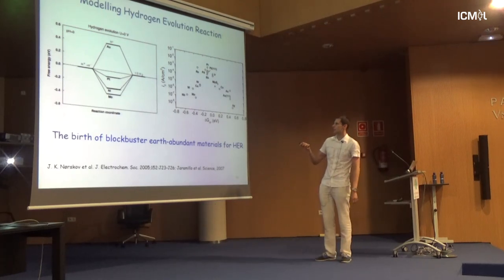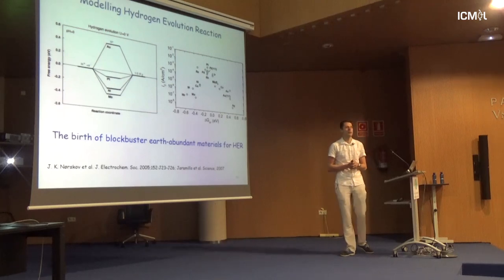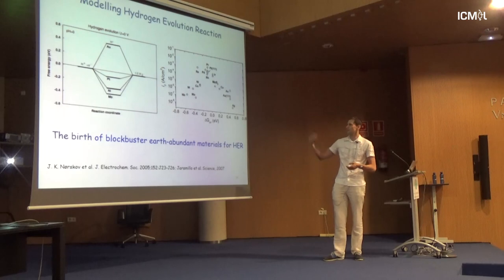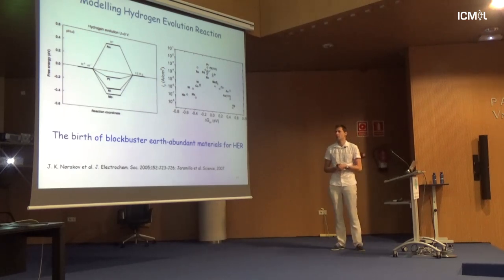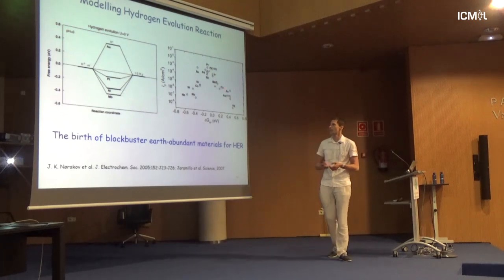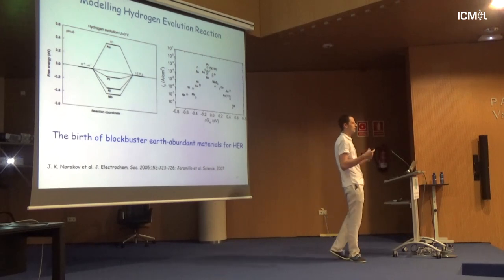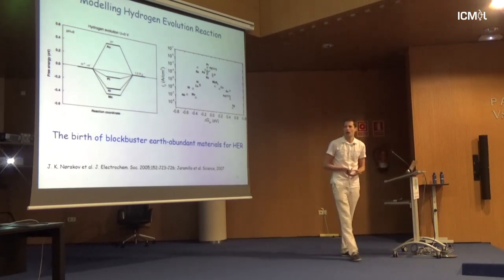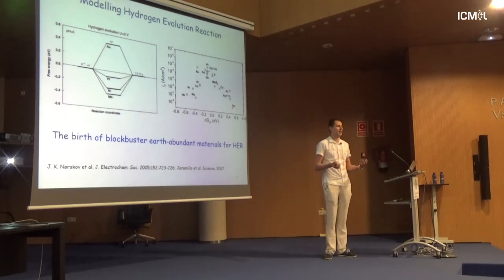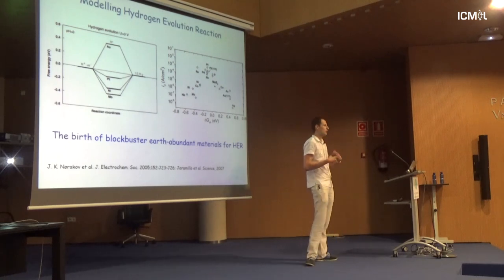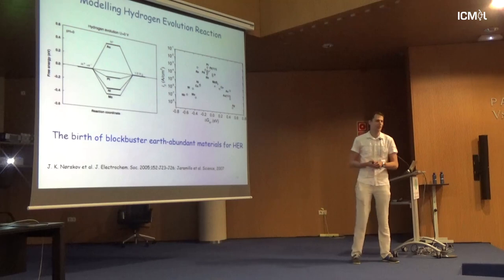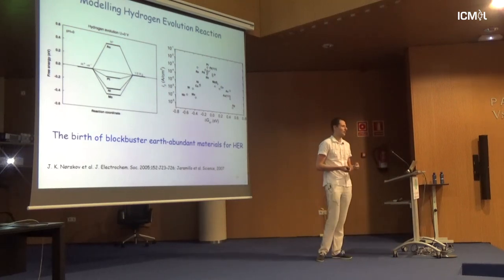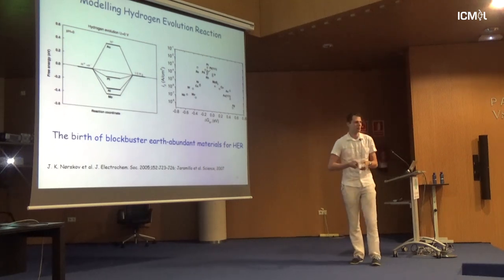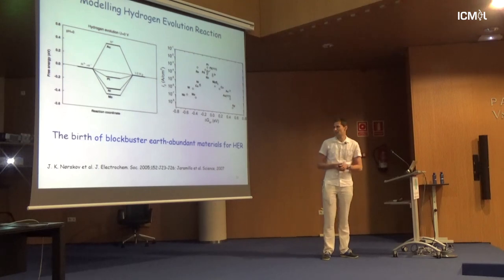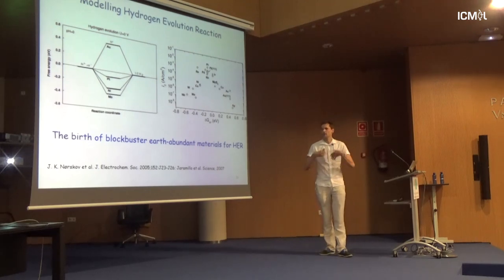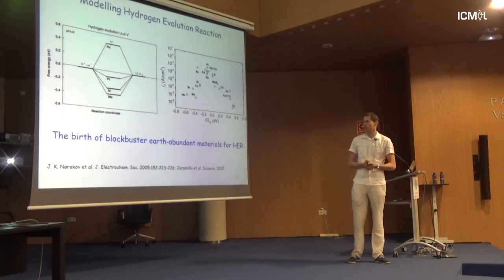So it's a very interesting trend, but what happened is you have a so-called burst of blockbuster materials, a burst of abundant materials, and what is very interesting, it coincided with graphene. So graphene arose around 2005-2006, and quite randomly, people started very actively calculating molybdenum sulfide, and if you calculate hard enough, then you probably demonstrate it is a very good catalyst. So there was enough effort and trial and error, and molybdenum sulfide was proven to be an absolute blockbuster catalyst. For whatever reason, it was at one time. And this trend continues to nowadays.